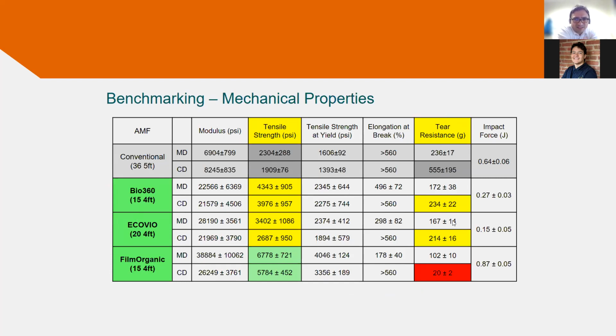And what does the tear resistance mean? For instance, this film organic had a low tear resistance in the cross direction. What that meant is that any puncture or any crack will result in a full crack propagation, and it will stop completely the lane mulch process, and it has to be restarted. However, the team was able to find ways around and lay some of these films, including the film organic here. And we can see also that these films have considerably good tensile stress.